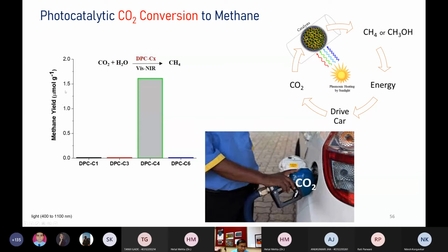The drawback here is, if you look at the y-axis, the methane yield is 1.5 micromole per gram, which is very poor, right? This will not help you to drive your car. But if I can make that to say 1500, or 1.5 millimoles or something like that, and very fast, say in 10 minutes or less than that, those numbers can vary, then this dream is feasible, and that's where the role of a chemist can come in, right? Where you will maybe one day have a car which will run by the sunlight and the catalyst and water and CO2, and it's all how we develop the catalyst, how we use the chemistry: organic chemistry, nanochemistry, inorganic chemistry, analytical chemistry, chemical engineering.